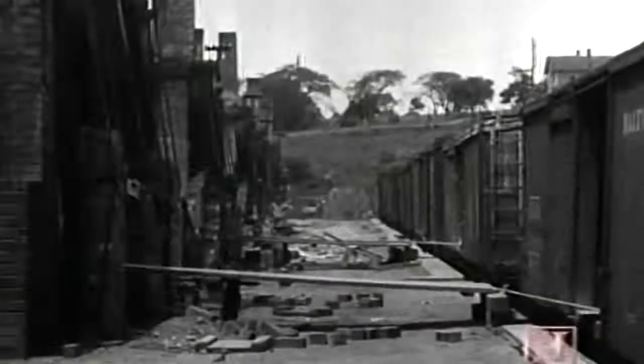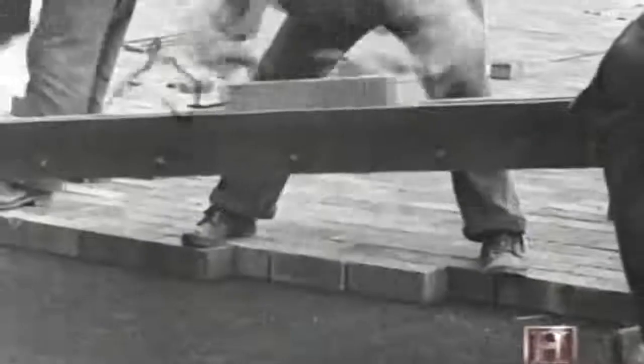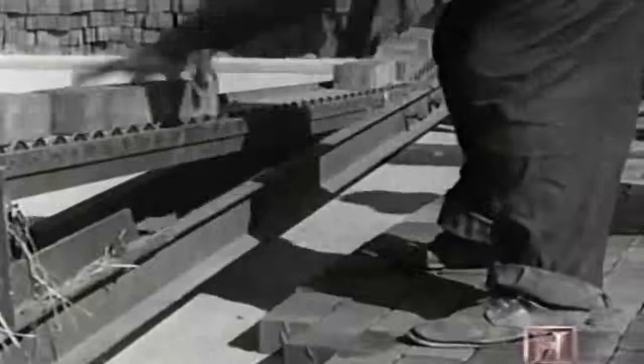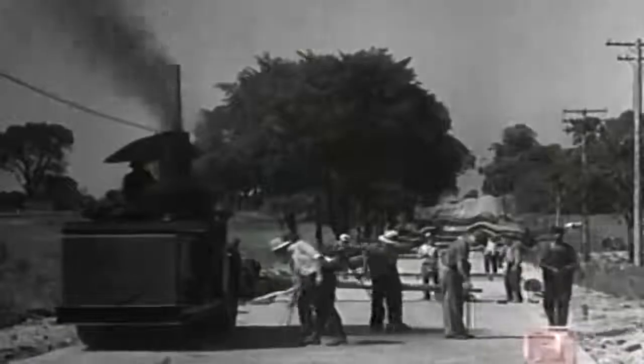Hudson River Valley bricks were primarily face brick or architectural brick and encompassed all applications above the ground. But bricks from other parts of the country with denser clay deposits could be used on the ground as well. Paving bricks are a very special type of brick that is quite different from building bricks because they are far denser in order to make them resistant to water absorption and to give them much greater strength, which they would be required for the beating that they would take on the ground.